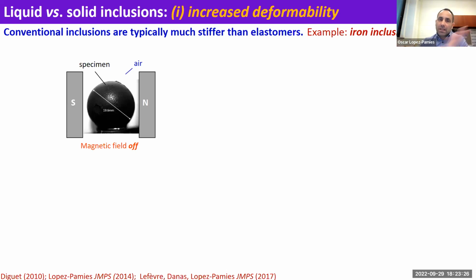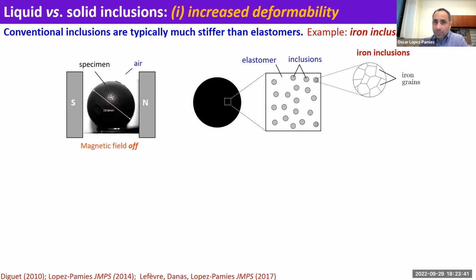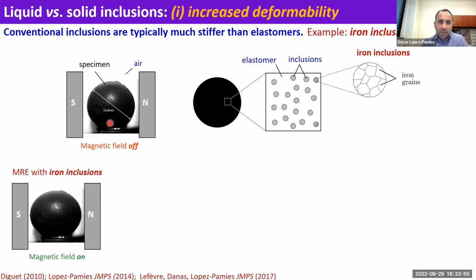This is a piece of rubber. This is a so-called magnetorheological elastomer. The matrix is rubber. It's not sensitive to a magnetic field. You can put iron inclusions in it, and this is an example of that. The idea that people were pursuing about 20 years ago or so was, okay, maybe we have an actuating system here. We can apply a magnetic field, and the thing is going to do something for us. And then maybe we can think of applications, right? And certainly people have thought of applications. It's nice to be able to actuate something with a magnetic field because it's a non-contact technique, right? You apply a magnetic field without touching the specimen.